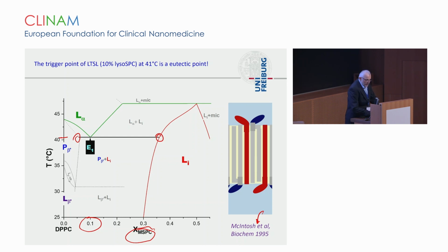So the idea is the following. A head group needs about 65 angstrom squared in area. A stretched chain needs of the order of 21 angstrom squared. So one head group can nicely cover the area of 3 chains. So if you have a monolayer and some head groups on this side and some head groups on this side, you can see that you can do this best at a 1-to-1 mixing ratio, then you can get a very stable phase.